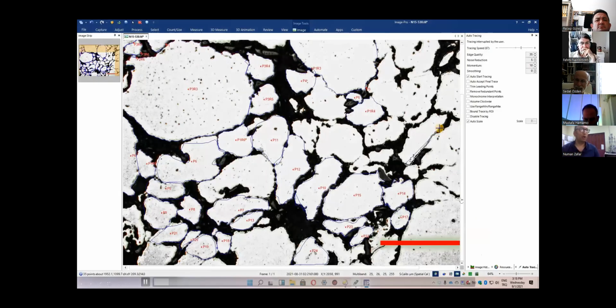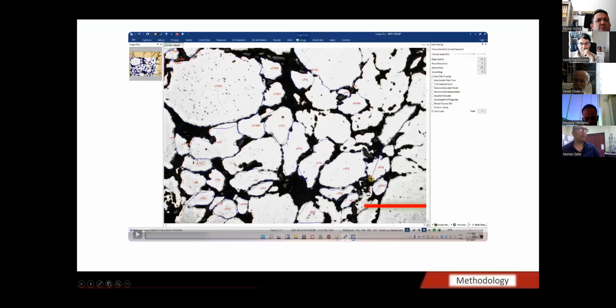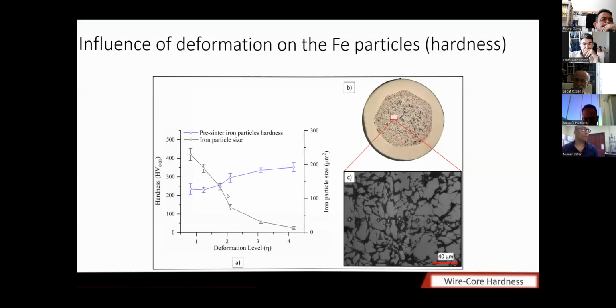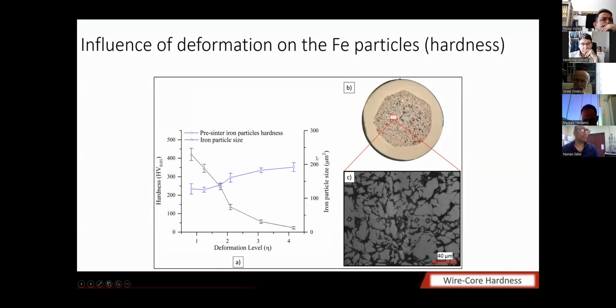Here is the methodology which I use to measure the iron particle size. I tell the software to treat the white color as a foreground and black color as a background, and measure the size of the iron particle. And the rest is all on me, what I want to measure and what I want to do with this iron particle. I did this to all these particles at most deformation levels. And then I reported these iron particle sizes.